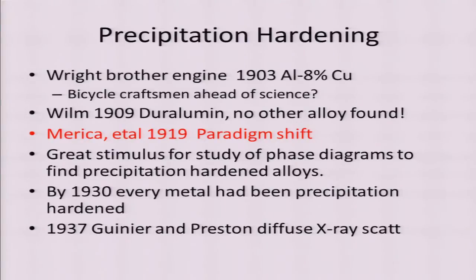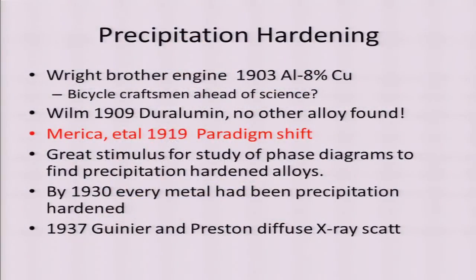And we in our field date precipitation hardening to Wilm's discovery in 1909 of duralumin. This was an alloy that he was testing the hardness of. Aluminum was useless. It was much too soft. It couldn't be used for anything. And he made a test of its hardness on Saturday just before going home for the afternoon. In those days you worked 5.5 days. Came back on Monday and decided to test the hardness again, and this alloy had gotten harder over the weekend. And that became the big commercial alloy that was used for airplanes in the First World War and was around everywhere. But 6 years before, the Wright brothers specified that their aluminum engine be cast of 8% copper by weight.